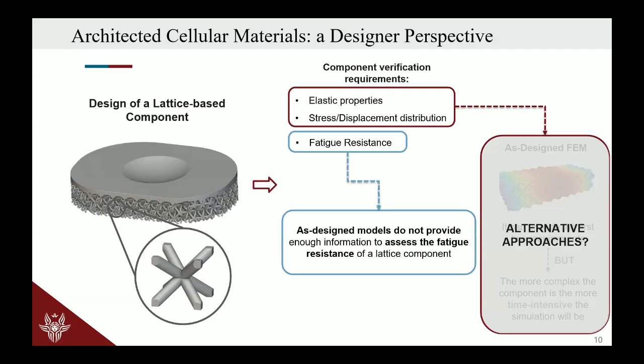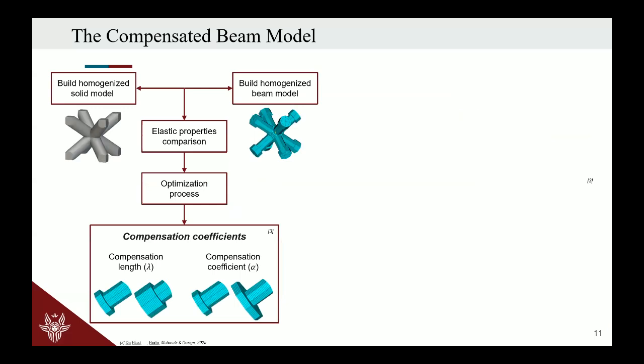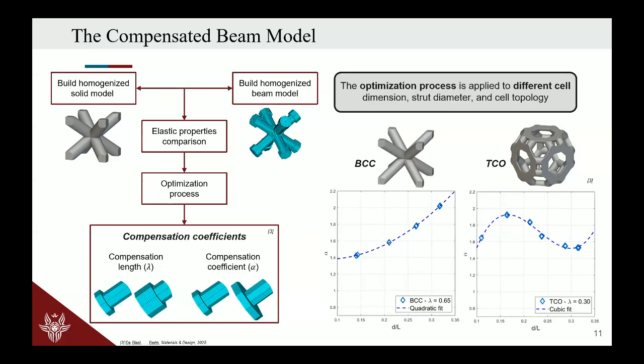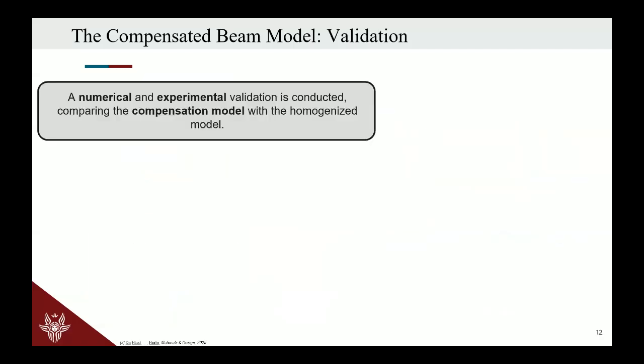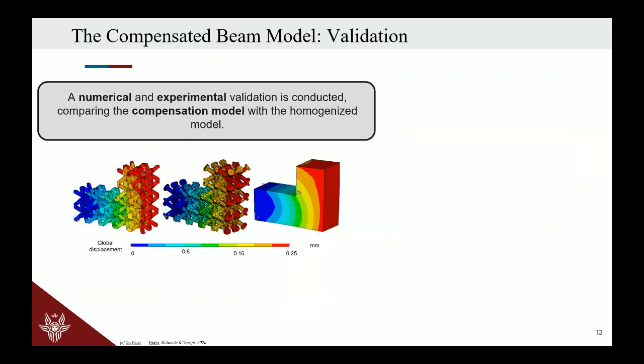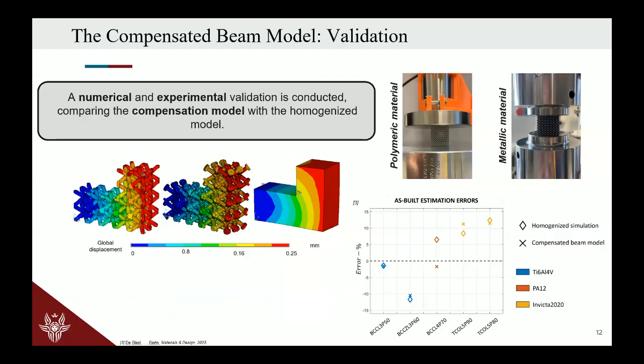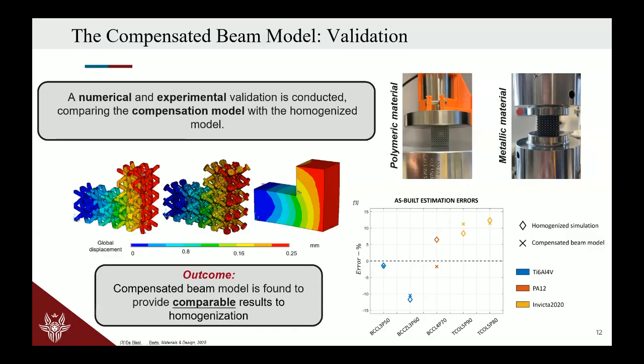So what we tried to do was to create a simple model to represent these cellular structures. In particular, we proposed inside this project a compensated beam model that was set up and also validated to show that it was able to fit the real behavior of the real lattice structure. A numerical experimental validation has been conducted comparing the compensated model with the homogenized model. What we obtained is that there is very little variation, if you see the graph on the right side of the diagram, between the homogenized model and the lattice beam model. So the outcome is that the compensated beam model is found to provide results comparable to the homogenization.